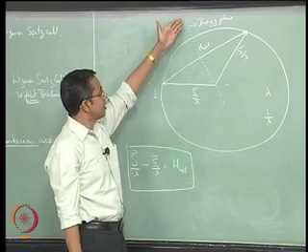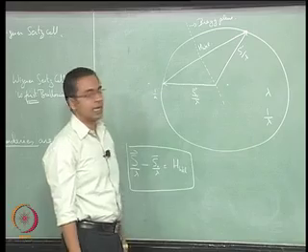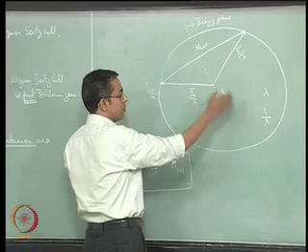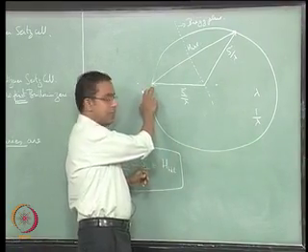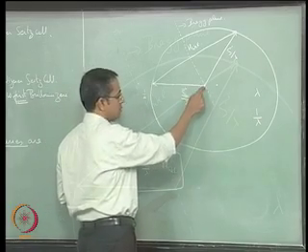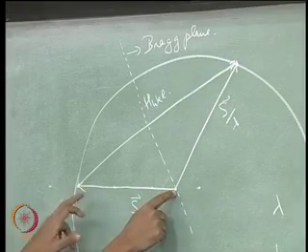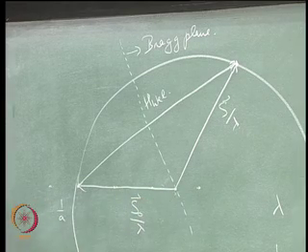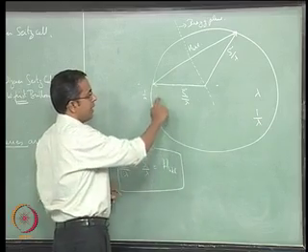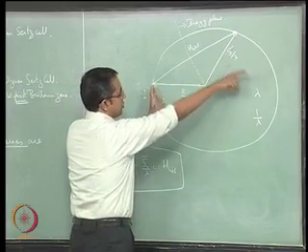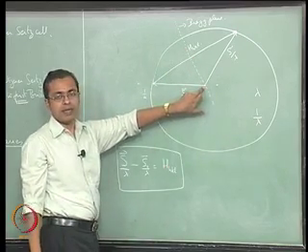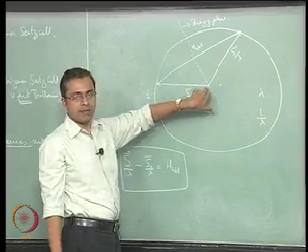So we see that a perpendicular bisector to a reciprocal lattice vector passes through this point. That is the origin of this circle, but it is not the origin of reciprocal space. The origin of reciprocal space is sitting here. So this is the origin of reciprocal space, this is the origin of the circle. That circle basically is defined by the ends of the wave vectors. In fact for this to be true, regardless of how you move this, always that bisector would have to go through this particular point, only then you are going to have diffraction.